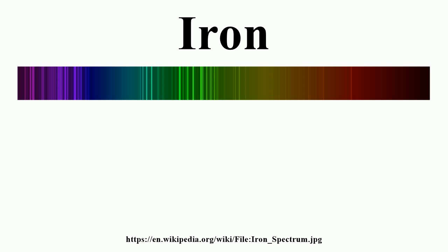The most abundant iron isotope 56Fe is of particular interest to nuclear scientists as it represents the most common endpoint of nucleosynthesis. It is often cited, falsely, as the isotope of highest binding energy, a distinction which actually belongs to nickel-62, since 56Ni is easily produced from lighter nuclei in the alpha process in nuclear reactions in supernovae. Nickel-56 is the endpoint of fusion chains inside extremely massive stars, since addition of another alpha particle would result in zinc-60, which requires a great deal more energy.